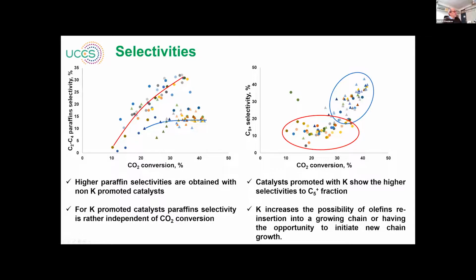Also here there are two trends. Here the top trend is for the catalyst which were not promoted with potassium. So we see if the catalyst was not promoted with potassium, the selectivity to paraffins increases as a function of conversion. However, for the catalysts which were promoted with potassium, containing different elements, we have almost stable selectivity to paraffins. So what happens on this catalyst? When we increase the conversion, you see that light olefin selectivity decreases. However, at the same time, we have an increase in selectivity to long chain hydrocarbons. So for that, we suggest that there are different paths on the catalyst without and with potassium. Without potassium, if we increase the conversion, we produce light paraffins. With the catalyst with potassium, we produce long chain hydrocarbons.